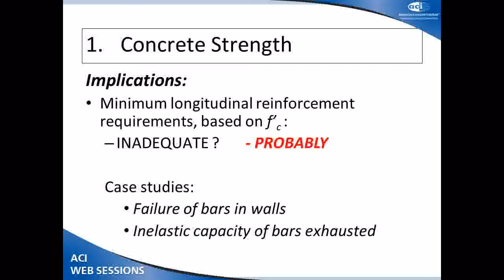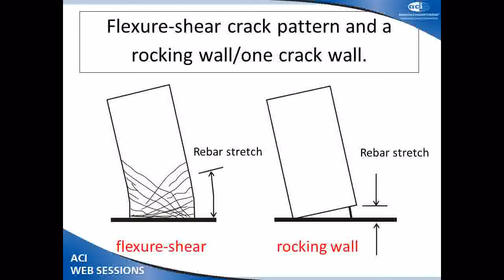As a general rule, we expect the minimum steel contents, particularly in walls and some beams, were not enough to start with. And then if you add in the fact that the tensile capacity of the concrete is significantly larger, you find that we do not have enough longitudinal reinforcement to form a distributed crack pattern and spread the plasticity. Any one or two cracks open up, and that plasticity is confined to a short length of bar. And here's a couple of case studies.